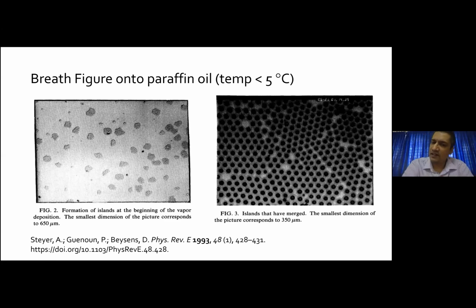So you can also think of the soft material as having some kind of a segmental motion, flexibility is there, so the molecules tend to align into hexagonal patterns. And surprisingly, unlike other glass surfaces in the earlier cases, they observed the formation of several islands, and these islands gradually started growing. And once the islands meet the boundary of the neighboring island, they coalesce, and you can clearly see the boundaries of the islands.